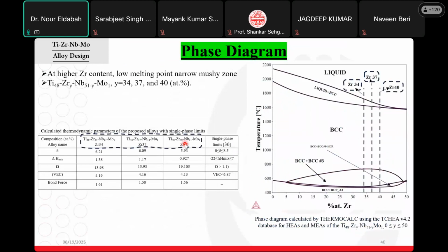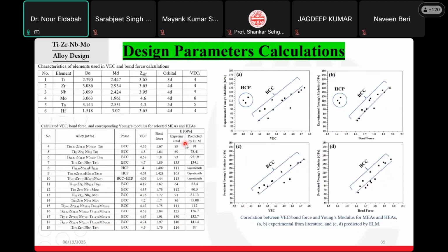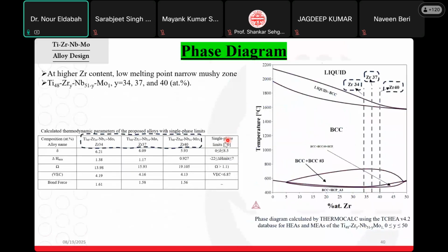The conclusion stated that your alloy should be a single BCC with a low valence electron concentration lower than 4.2, and a bond force lower than or around 1.6, in the BCC phase. If you plot a phase diagram in titanium-48, this region was strongly recommended by the machine learning, and if you use the Thermo-Calc software to draw the phase diagram, it will give you this phase.